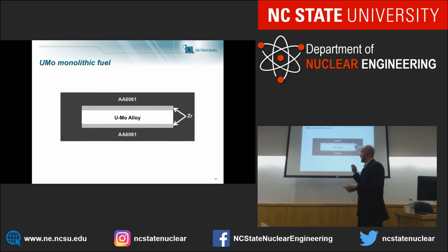In these types of fuels that are implemented in research reactors, we have a U-Mo fuel foil, with a diffusion barrier in these systems, that is fully encapsulated in aluminum clad. So all the fission gas stays inside, has to stay inside. It's a very different kind of situation that we're dealing with. We really need to understand the swelling behavior, how the fission gas evolves, and what kind of effects we're going to encounter from not allowing the fission gas to leave the fuel.